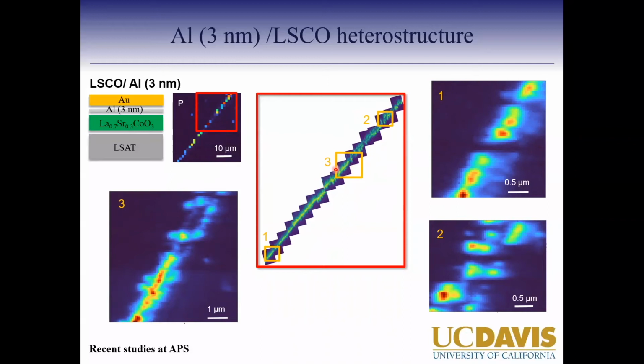So it almost looks like you have these, and again, the contrast here, yellow now means brownmillerite, and the dark means perovskite in this case. And it almost looks like you have different brownmillerite regions which got converted, and they always cluster around this 45-degree angle or so. And where we had higher oxygen deficiency, we saw this continuous formation, but where we had low, this is in the initial stages of formation. And that could be because the amount of oxygen vacancies created by aluminum 3 nanometer is slightly different from gadolinium 3. So we missed out on this transition because we got into more homogeneous filaments by that point.